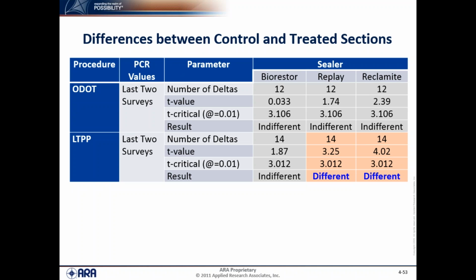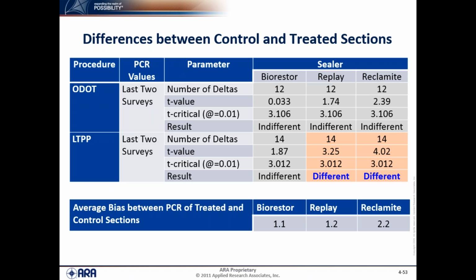between the control and the PCR of the treated sections. And again, we calculate the t-value and the critical t-value for the paired t-test. And now we can see two of the sealers did make a difference. The Replay showed a difference, and the Reclamite, where we can say statistically there's a difference between the control as well as the treated sections for those two. So that was done by a paired t-test.